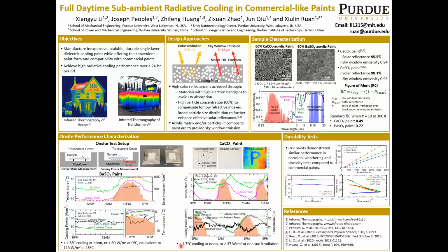Calcite paint achieved over 37 watts per square meter cooling power at noon, and barium sulfate paint reaches over 80 watts per square meter even at 0 degrees C, equivalent to 113 watts per square meter at 15 degrees C. Additionally, we painted a P pattern with calcite paint, while the background was painted by commercial paint. On the regular camera, the pattern was hard to see. However, it became very distinctive in the infrared camera, as the cooling paints stay cooler under direct sunlight.